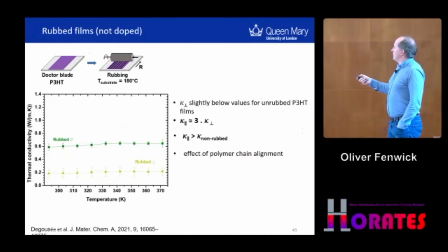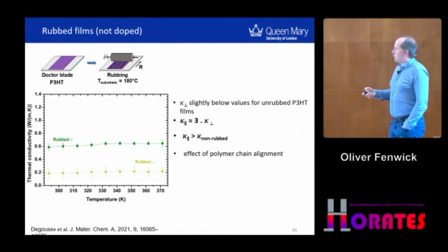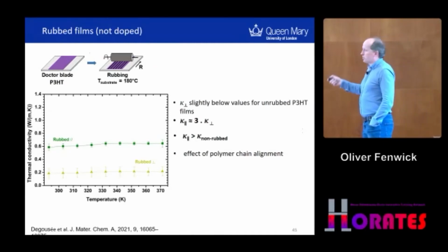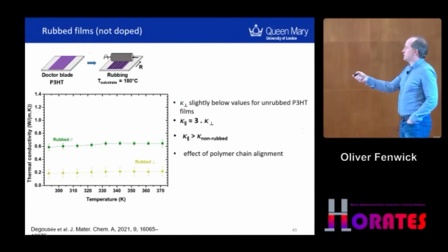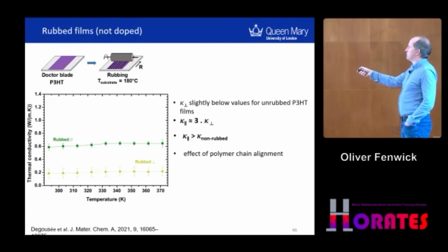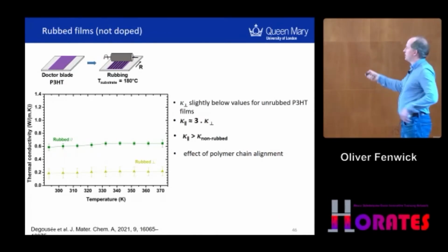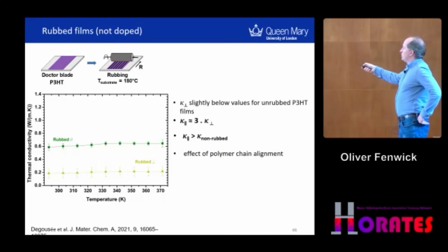So what about the thermal conductivity? Well, now we have a significantly higher thermal conductivity along the chain-aligned direction, so about 0.6 watts per meter Kelvin. If we measure in the other direction, it's only 0.2 watts per meter Kelvin, so still very similar, slightly lower than our previous value, but still within error bars similar to what you'd expect with P3HT. So we can see a clear effect of the alignment in the thermal conductivity.